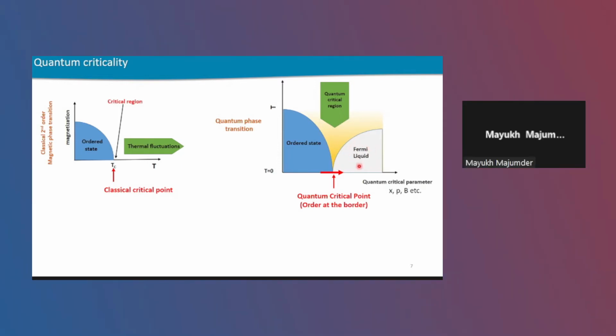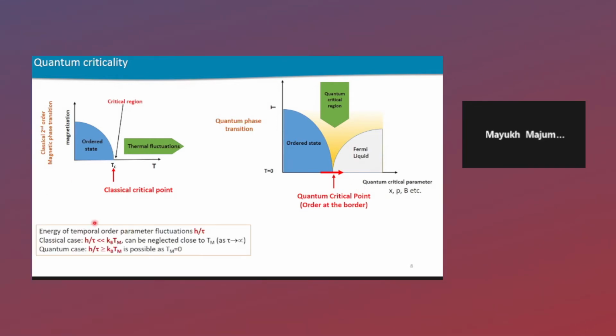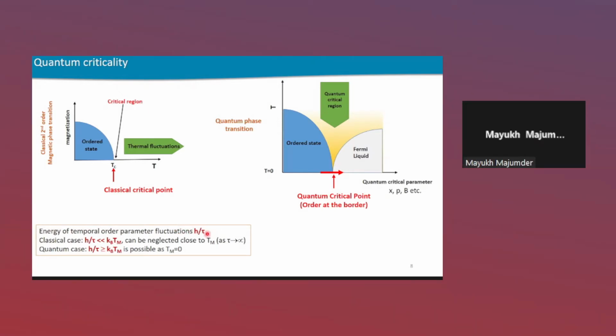Just to tell you what interesting behavior one may expect in the region around the quantum critical point: we all know that for any phase transition, at the transition temperature, the spatial as well as temporal correlation length diverges. Now, consider that the energy associated with the temporal order parameter fluctuations is h over tau, where tau is the correlation time. For the classical case, a second order magnetic phase transition, the ordering temperature is finite, that is non-zero, and as I just mentioned, tau diverges to infinity.